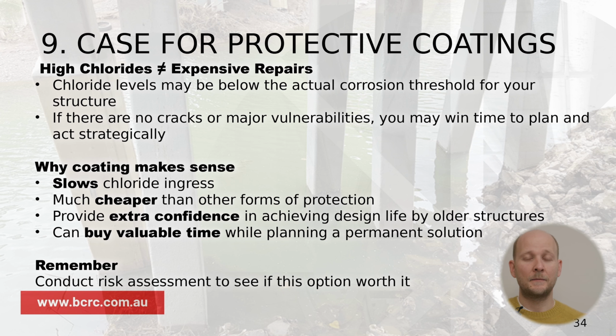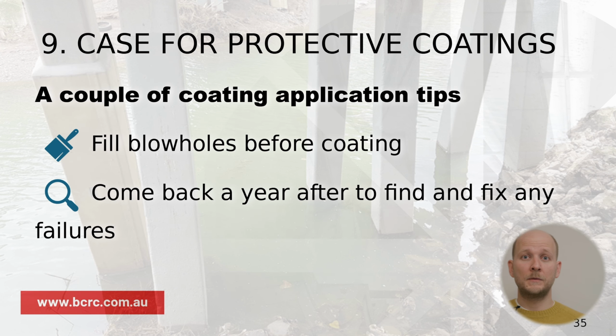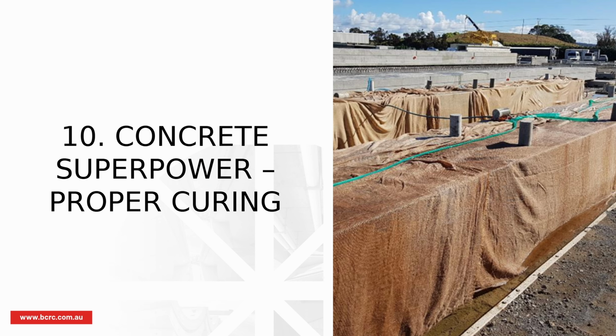Coating makes sense because it slows chloride ingress, and it's much cheaper than any other options typically available for repair. It gives you that extra confidence and it buys you valuable time to plan for the next repair, as I say. But what's important is to consider all the risks associated with it and make sure you did the risk assessment. A couple of tips here. Fill all the blowholes before you apply coating, because these blowholes could be entry points for salt water. And come back a year after to inspect your coating. Make sure that it's intact and undamaged. You will be surprised, even with good QA of your findings. At least I was on one project.